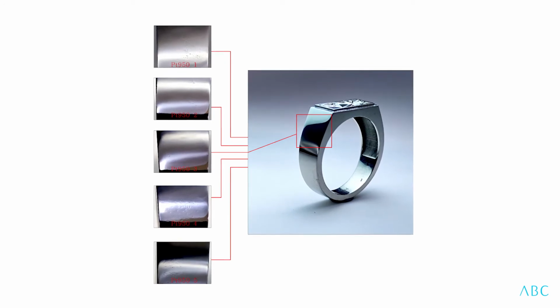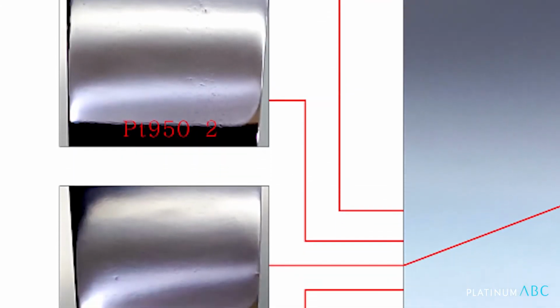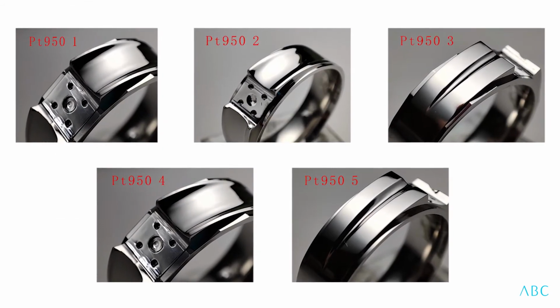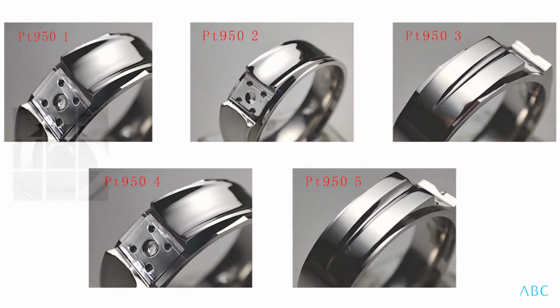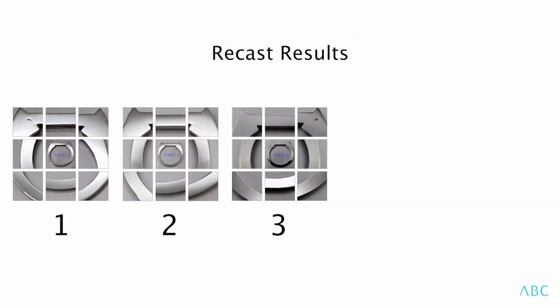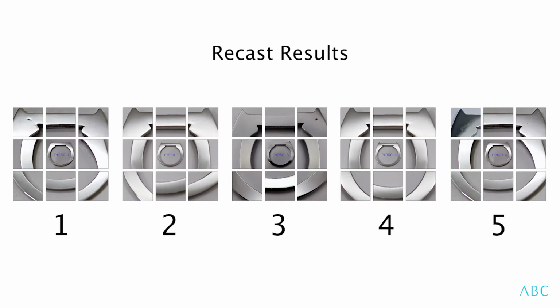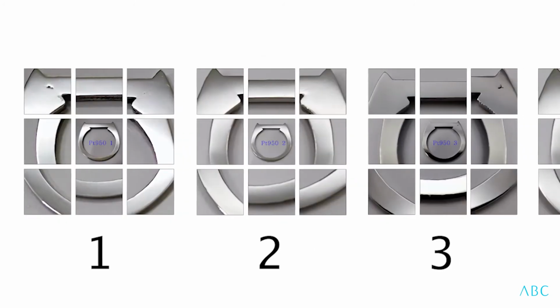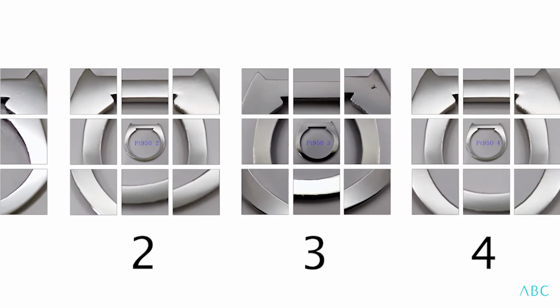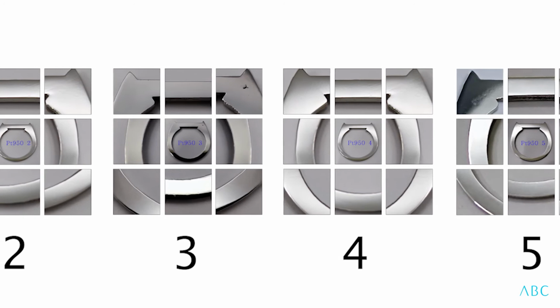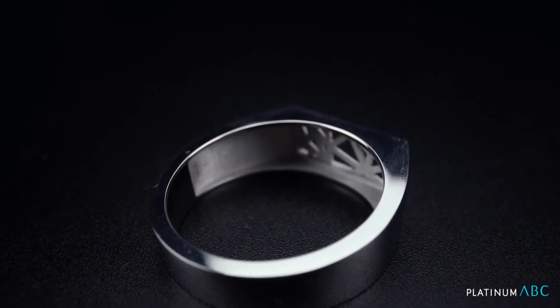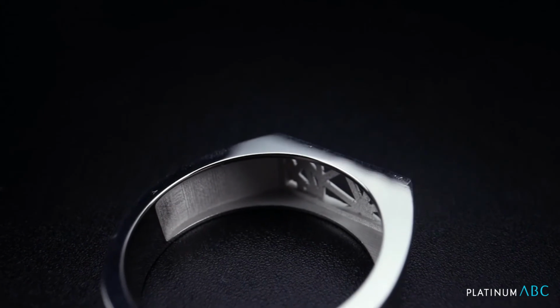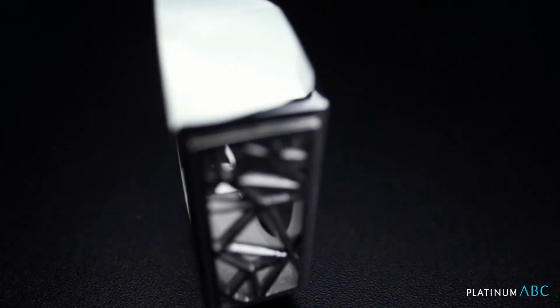To be very honest, we were expecting some levels of contamination and deterioration in performance in progressive reuse of the metal. There is porosity, especially on the surface of the heavy sections, but there is no evidence of an increase in porosity after 5 rounds of recast. Then our usual operator in the casting room took a day off and asked his assistant to do the recast. And on that 6th round of casting, something went very wrong. There was evident increase in porosity. Clearly, something was done differently in the casting process that resulted in a decline in quality.